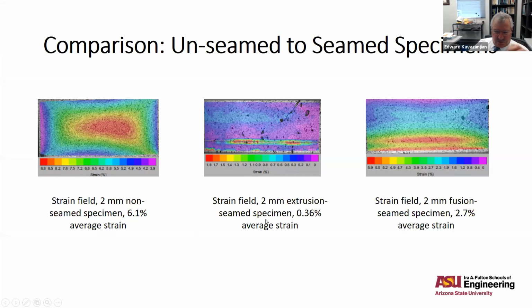So these are those blobs of resin that we use to hold the seams together. This is the edge of the seam that's going into bending. Here, the average strain on the seam was just 0.36%. If we look at the code down here, we see some areas of red in the seam. We see a large area of yellow where the strain is on the order of 1 to 1.5%. And then we see some higher areas of strain where the strains were as much as 1.8%.